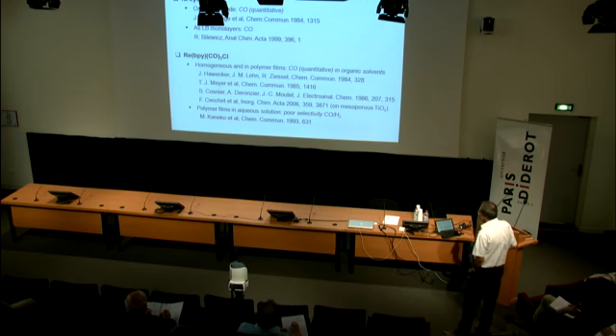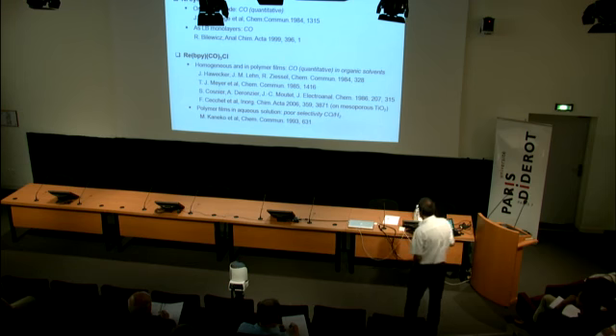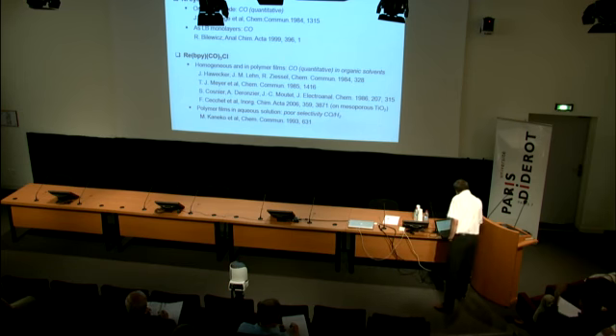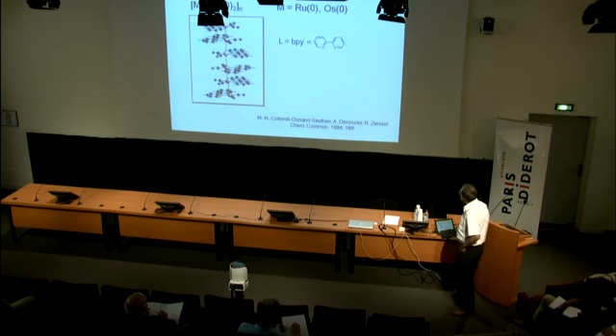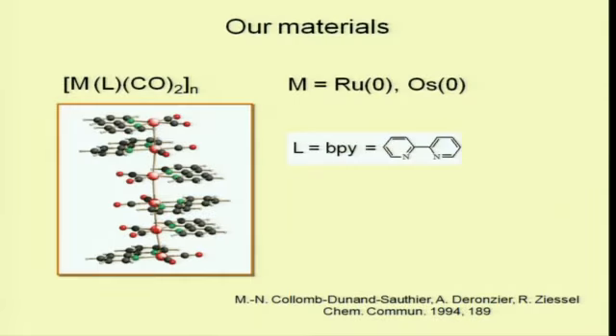If we try to use this system in aqueous solution, there is a poor selectivity, as for phthalocyanine, production of CO versus hydrogen. It's because the potential of reduction is too negative. So what we have done in this area, beside films of rhenium derivative.